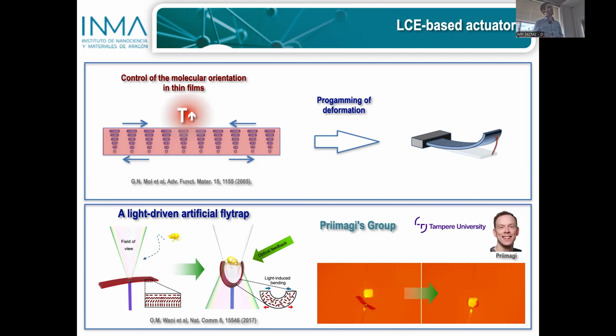Essentially, they have created a thin film of a liquid crystal network, having in this case a splay configuration, but essentially it's very similar. The deformation is essentially the same as in the TN mode. They pierce the film with an optical fiber.